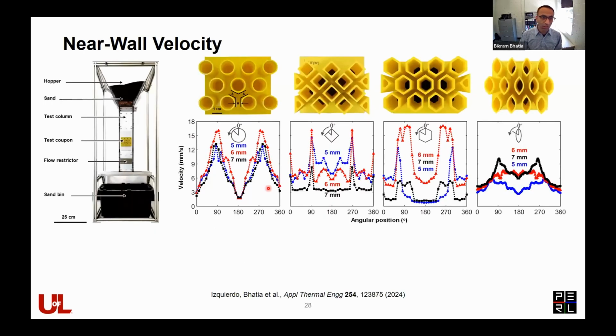So we looked at this problem in our lab, and we built this experimental test rig, which is shown here on the left. We have sand on the top. We have our test coupon, which is a 3D printed coupon of the heat exchanger. We are mostly interested in the solid particle to tube wall heat exchange, because that's the bottleneck. So that's what we've really focused on. And we use these test coupons to study this gravity-driven flow over tube bank heat exchangers. We did high-speed imaging of these falling sand particles around the tubes. Based on that, we can track different particles and figure out the velocity around the tube for different heat exchanger configurations.